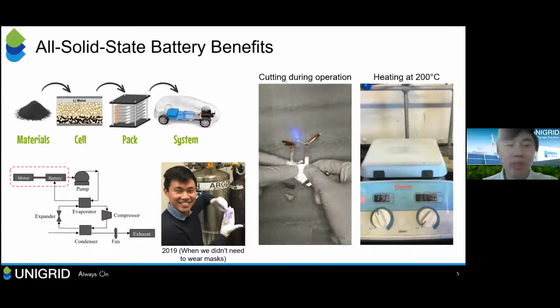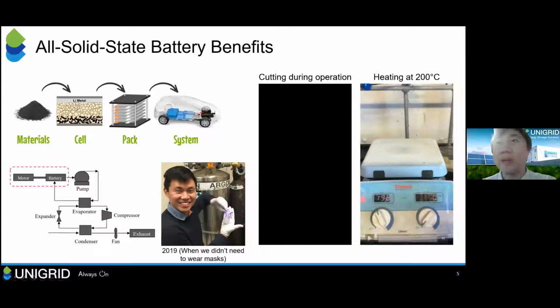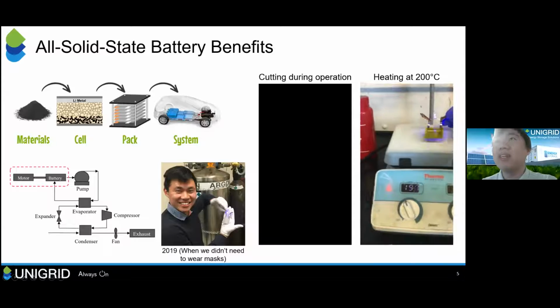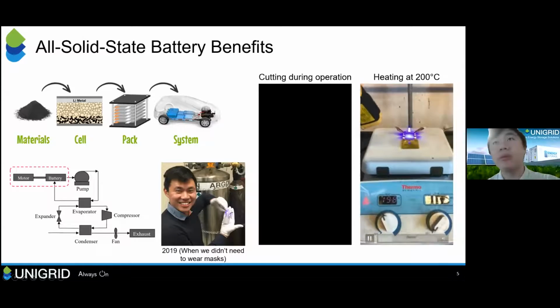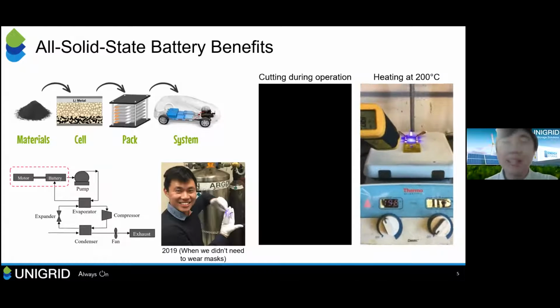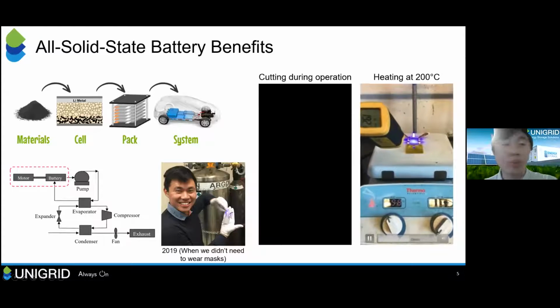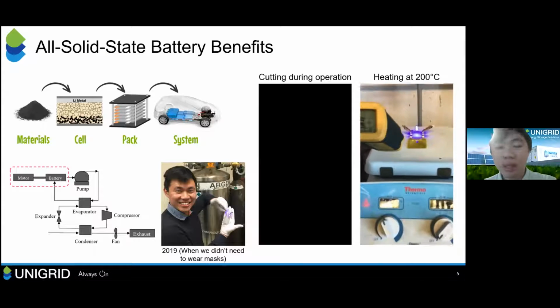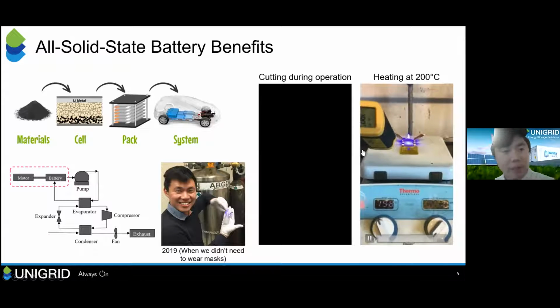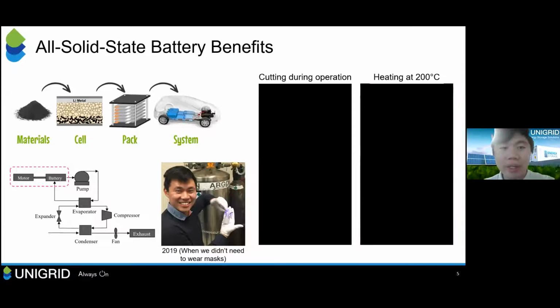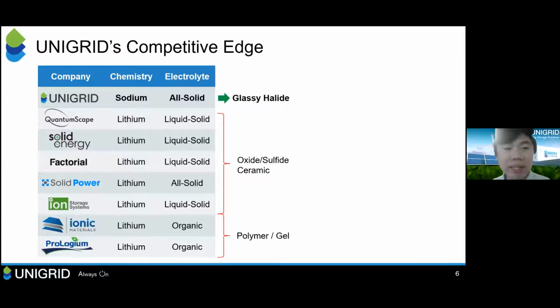Now, I highly recommend you don't try this for regular lithium-ion batteries. This is another video of us putting it on a hot plate at about 200 degrees Celsius. If this was a lithium-ion battery, it would swell very dramatically, and we would see unpleasant things start to occur. But in this case, it just sits there and does its job, to put it simply. So in other words, we show that it's very safe, and we can show that it operates over a wide temperature range.